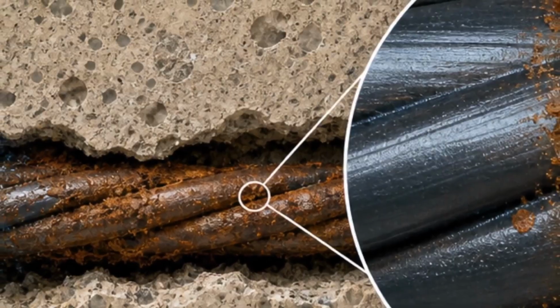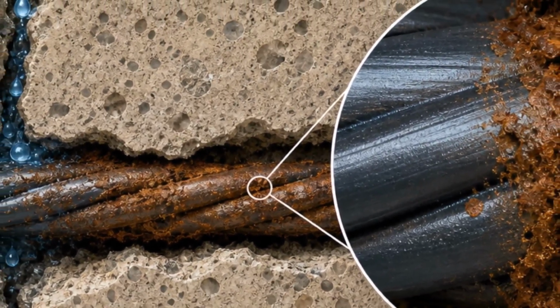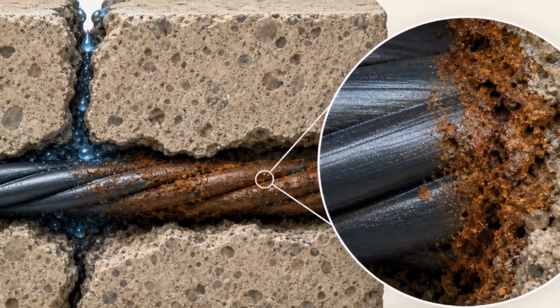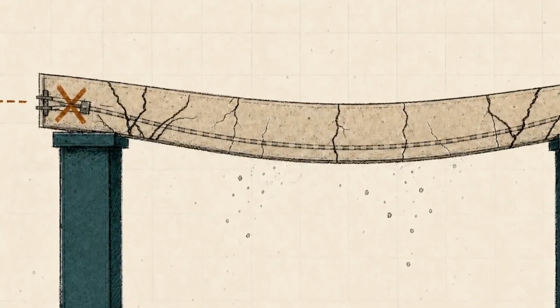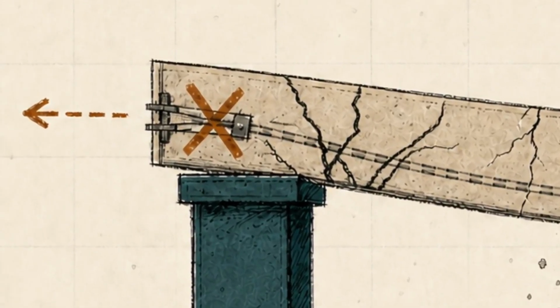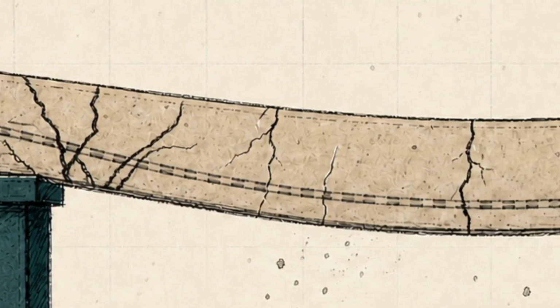As those of you who follow our channel know, these specific tendons were unbonded, meaning no protective grout. So once a single wire snapped, the loss of tension wasn't local, it traveled along the entire length. When those tendons corroded and snapped, the slab lost that vital squeeze. If you suddenly remove that active compression, the structure doesn't just sag, it fails instantly.